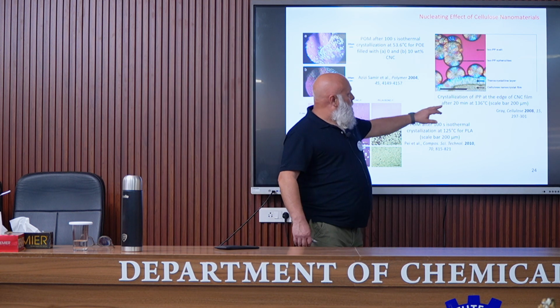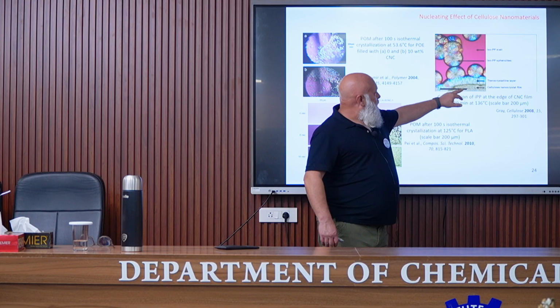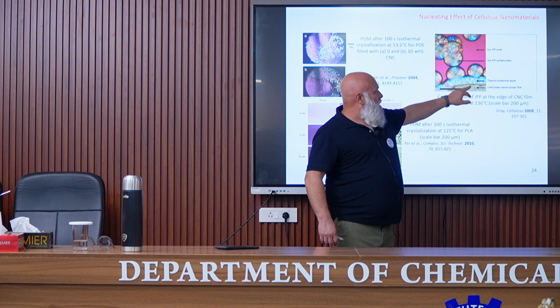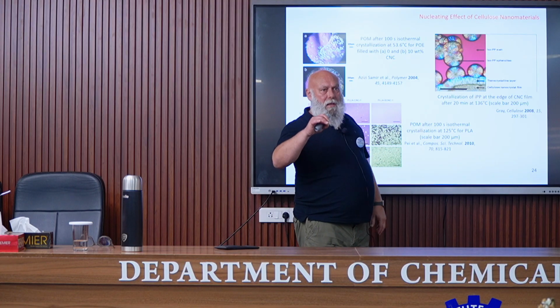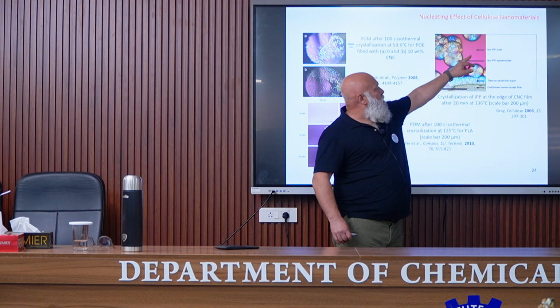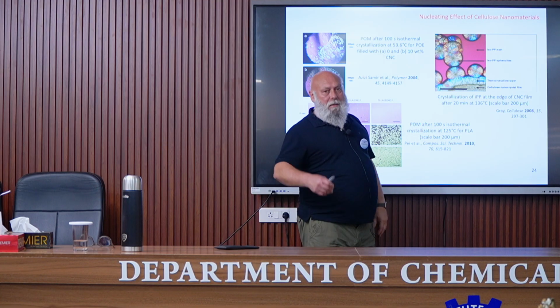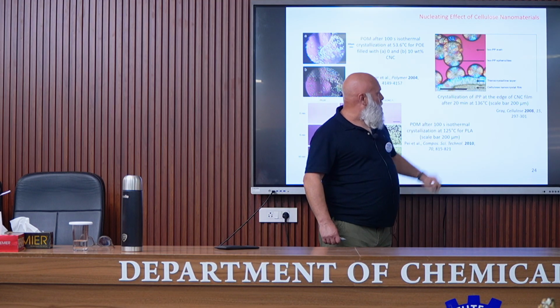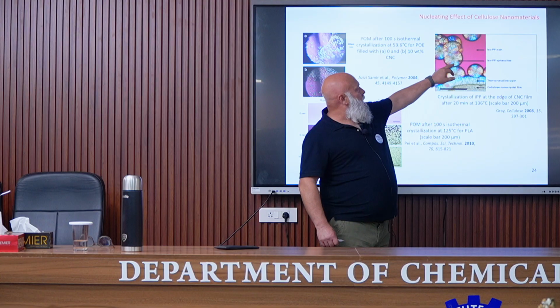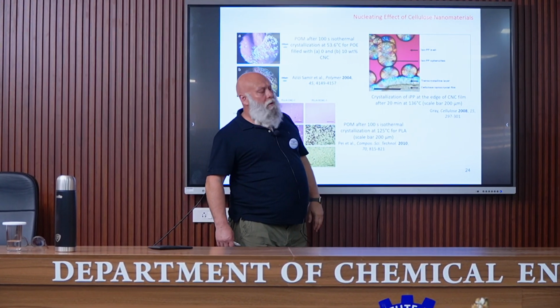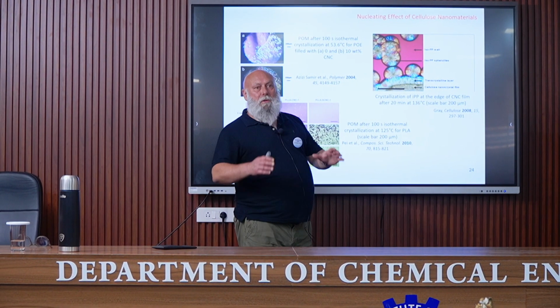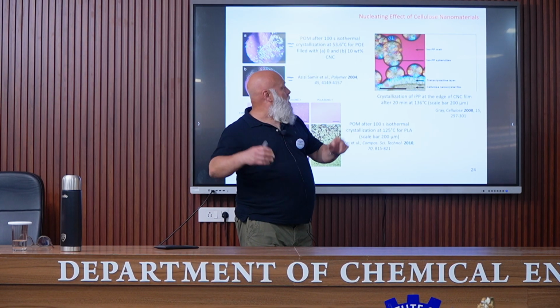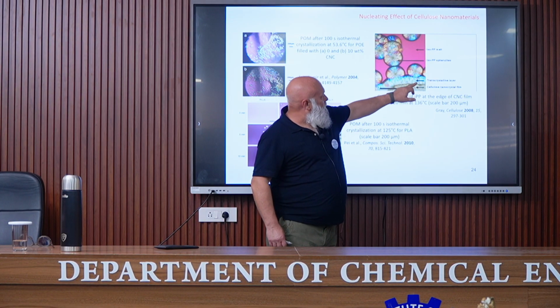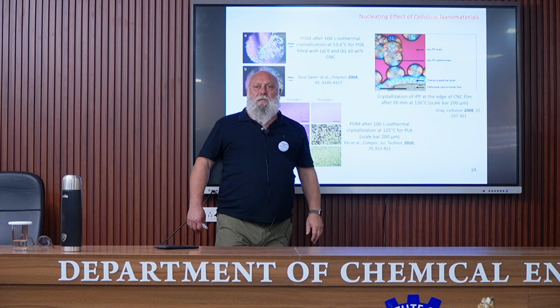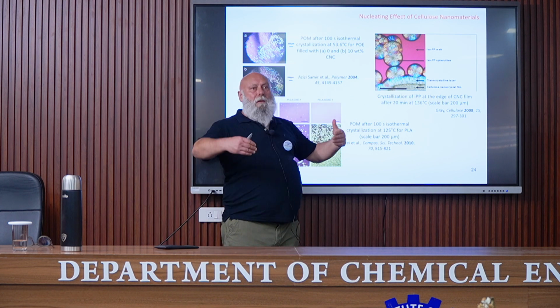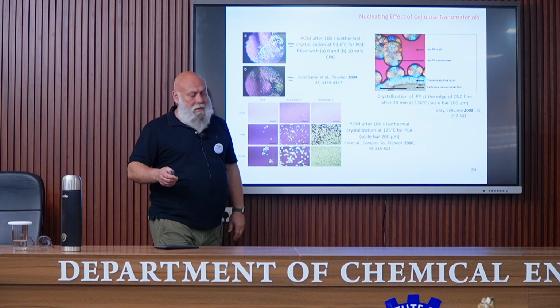This is another photo that I like very much, this one. This is a cellulose nanocrystal film, and it was immersed in an isotactic polypropylene melt, and crystallization was performed at 136 degrees. And you can see here polypropylene crystallization in the polymer in bulk, in the polymer melt, and at the surface of the cellulose nanocrystal film, we have this transcrystallization that can be observed.